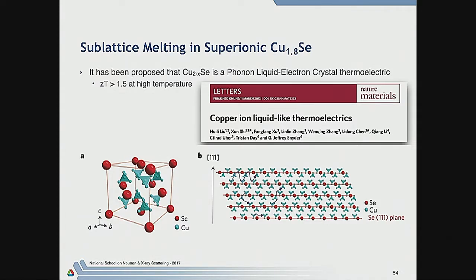Copper selenide is a material in which there are multiple copper sites within the unit cell that are partially occupied. And at high temperature, it goes through one of these superionic transitions where the copper ions become very, very mobile. Indeed, it was called by one group a phonon liquid electron crystal. It has very good thermoelectric properties. And in thermoelectrics, you want to have good electronic conduction, hence the electron crystal, that's not affected by the disorder. But you want to have very poor thermal conduction from the phonons. And in this case, they argued that perhaps some of the transverse phonons didn't even exist because the copper sublattice was disordered.